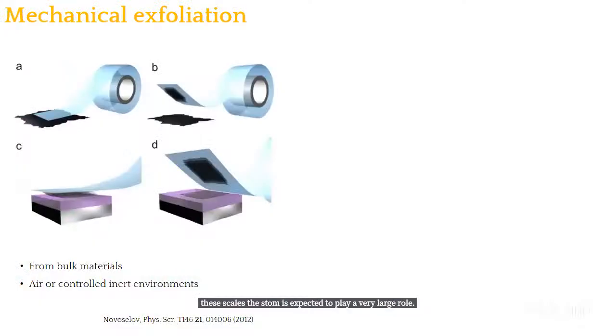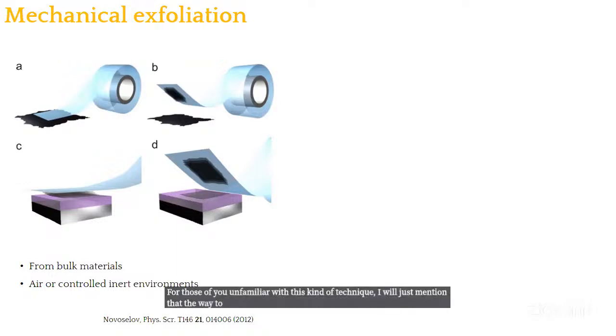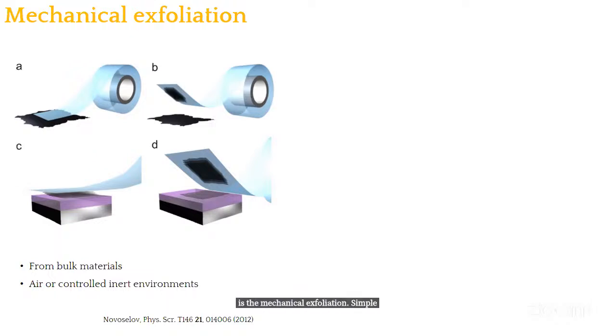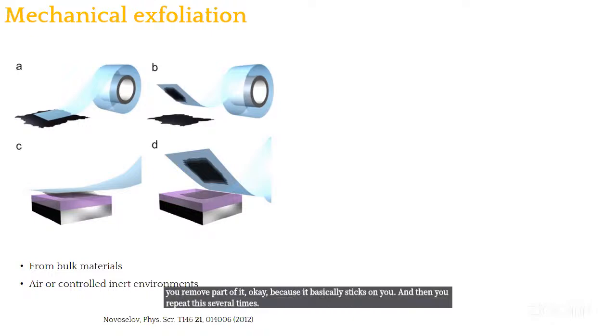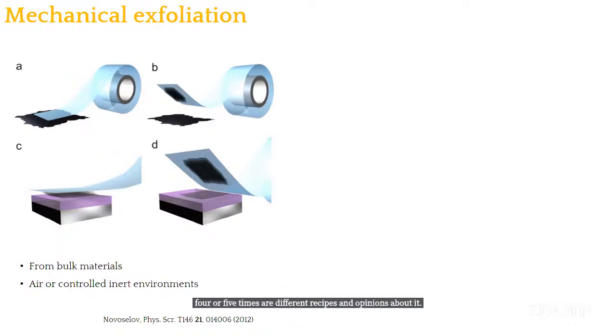For those of you unfamiliar with this kind of technique, I will just mention that the way to fabricate these samples is mechanical exfoliation. Simple as that. You take one Scotch tape, you approach it to a van der Waals material, you remove part of it, because it basically sticks on you. Then you repeat this several times, 4 or 5 times. There are different recipes and opinions about it. Once you are happy with it, all you have to do is stamp it on a particular substrate, in general silicon or silicon oxide, and then you look at the debris that you have left on top of it.